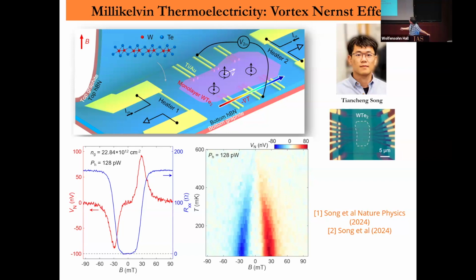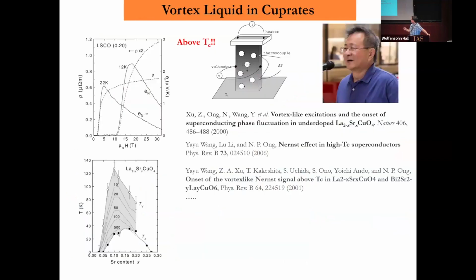And then as you warm up the temperature, you see the Nernst signal smoothly disappear, just like the superconducting transition. So this data tells us that in this device, we do observe Nernst effects arising from the vortex. Okay, so this is some background.